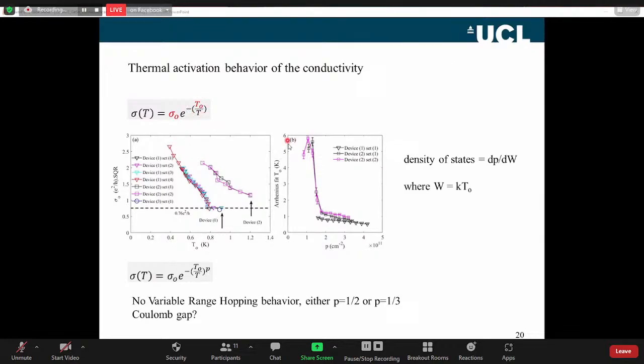If we plot out T0 as a function of carrier density, at high carrier density it's very, very metallic. It does show this thermal activation to a mobility edge. As we change the position of the chemical potential, that energy increases, and then at some point it increases very rapidly. It's almost like a transition. I wouldn't say it's a metal-insulator transition, but it's very, very close to one, a very rapid change of activation energy.